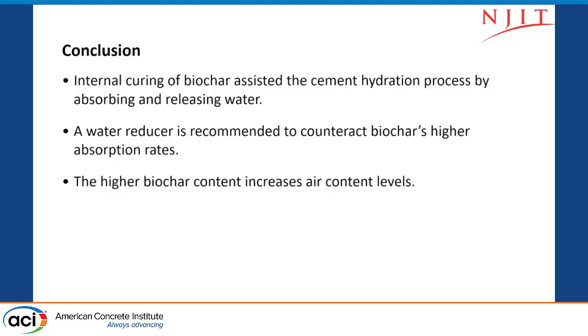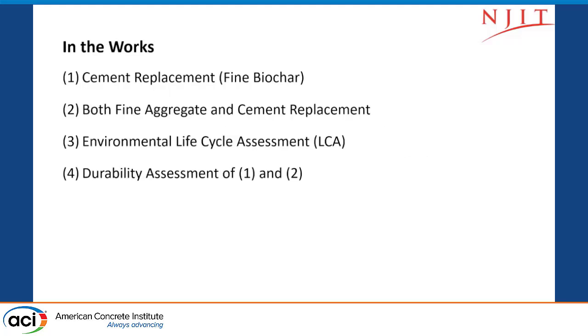Internal curing of biochar assisted the cement hydration process by absorbing and releasing the water. We use, of course, a high range water reducer, because when we started, the biochar absorbed all the water, and even the drum was not rotating smoothly because the biochar absorbed everything. And we were like, what's this? This is a very water-absorbing material, so we have to increase the HRWR. A water reducer is recommended to counteract the biochar's higher absorption rates, and the higher biochar content increases air content levels and other things, as we saw in the pictures.